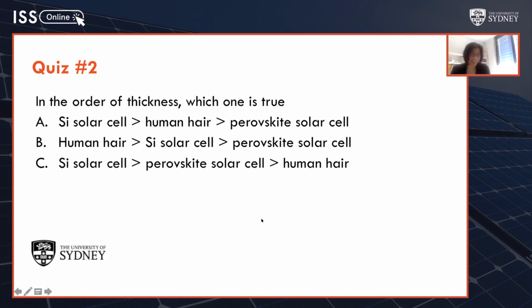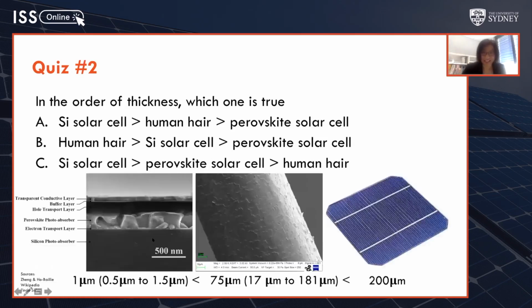Okay, well, the answer is A. Silicon cell is around 200 microns thick, which is thicker than a piece of hair. So you can hold it, you can carry it. And hair, depending on your genes, can be very thin and fine, or it can be thick. Mine's sort of in the 181 microns range. And the perovskite absorber layer was actually only 500 to 800 nanometers, plus all the other layers, the hole transport layer, electron layer, and the electrode is around 1 micron thick.